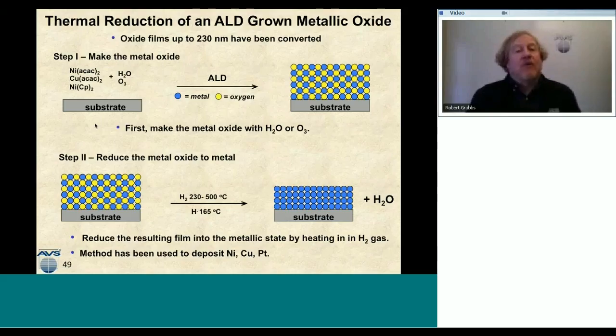So the third way is really just a thermal reduction of ALD. And so what I do is I make the metal oxide. I can use this organometallic precursor with water or ozone. I can use nickel ACAC or copper ACAC or nickel CP. React that with water and ozone, and I just make the metal oxide over here.